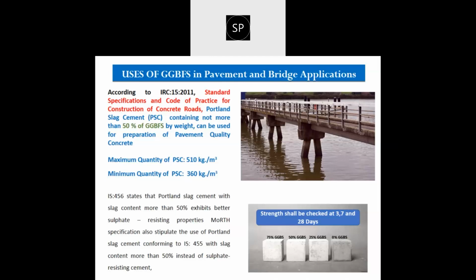IS 456 states that Portland slag cement with slag content more than 50% exhibits better sulfate resisting properties. The MORTH specification also stipulates the use of Portland slag cement conforming to IS 455 with slag content more than 50% instead of sulfate resisting cement. So in case of a marine environment, or where the concrete structure is going to remain submerged, it is better to use PSC in comparison to OPC and PPC cement.